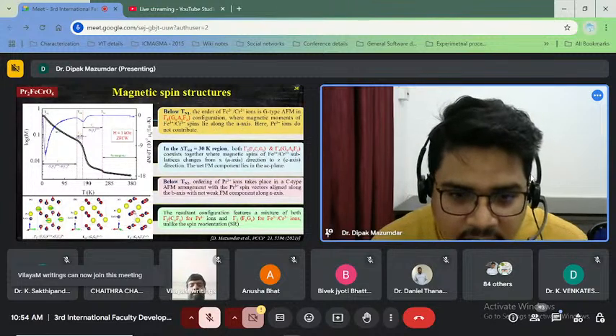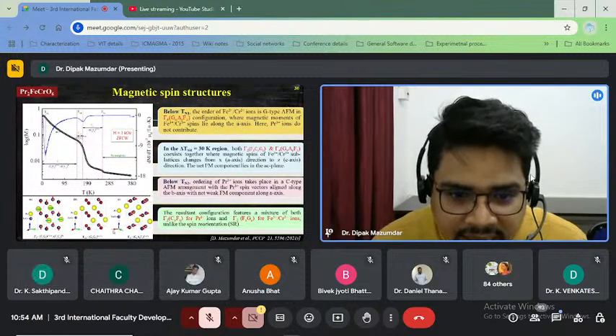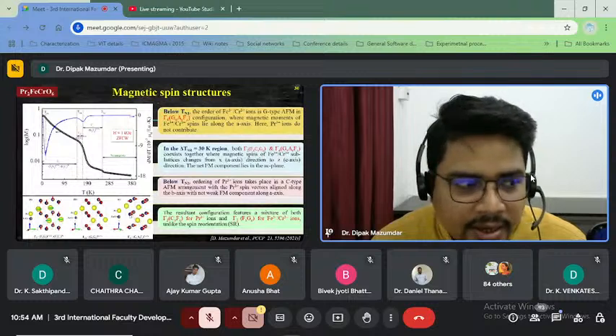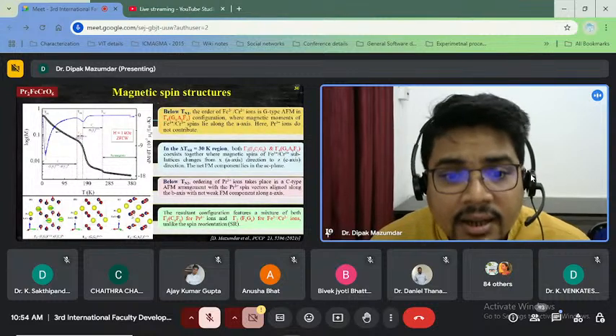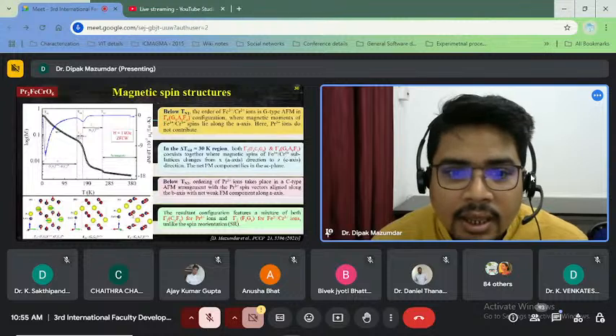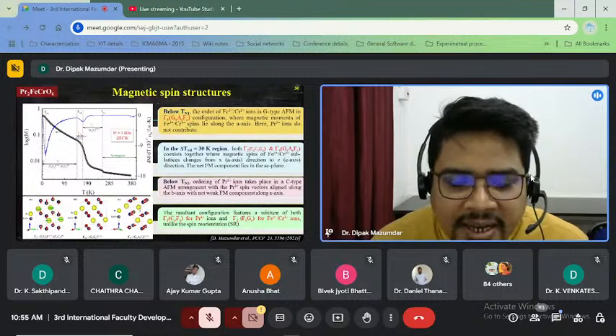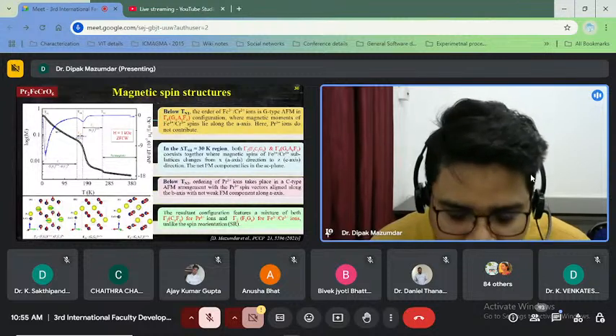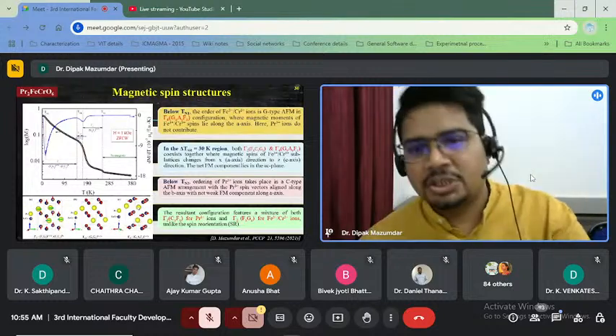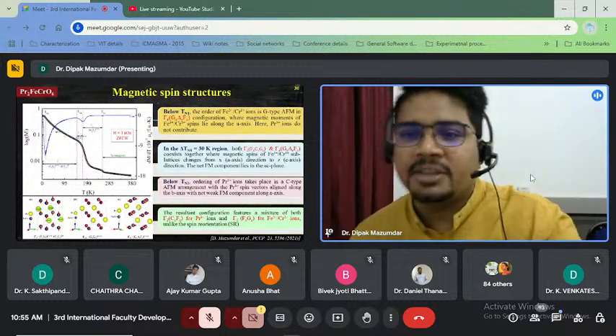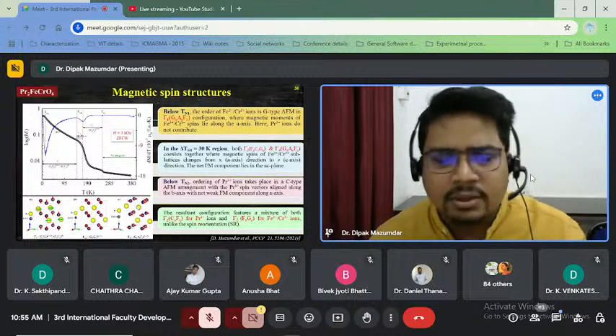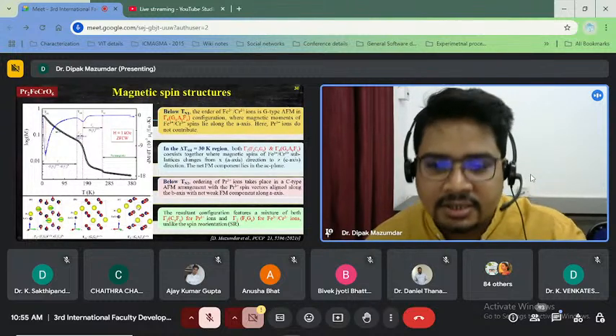You can see here, if it is the A-axis, so magnetic moments are lying along the A-axis, but they are antiferromagnetically coupled. You can see there is no magnetic moment I have shown for praseodymium, because at this high temperature praseodymium will not be active. So I did not mention this case.